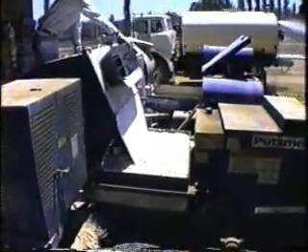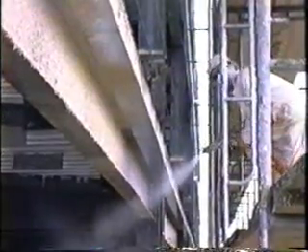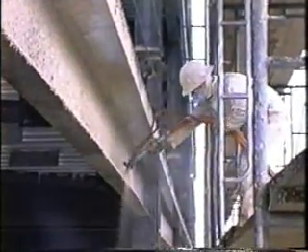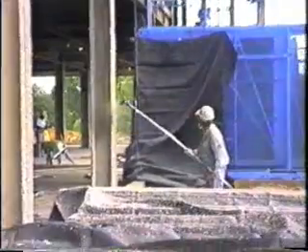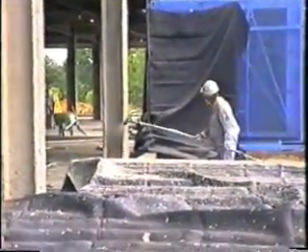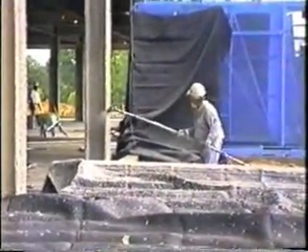Once all the pumps and hoses have been primed with water at the start of the application, the material is then ready to be discharged from the mixer into the pump hopper. The material valve at the spray nozzle is then opened and the pump switch turned on. When the slurry begins to exit the nozzle, the atomized air should be adjusted to achieve a uniform spray pattern. It must be made sure that there is no restriction of material.